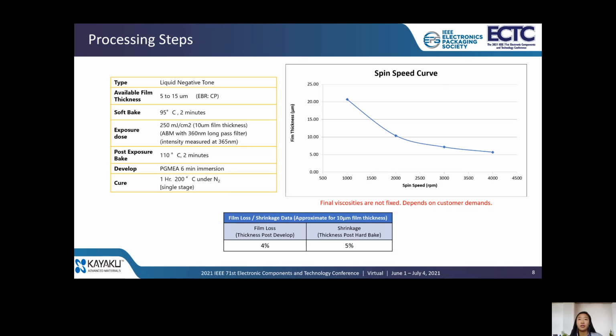After soft baking, this material undergoes a cure step via photoinitiator to cross-link the material. We recommend a 250 millijoule per centimeter squared exposure dose for a 10 micron film thickness, followed by a post-exposure bake at 110°C for 2 minutes, and this again is optimized for a 10 micron film thickness. This can obviously be optimized further for other film thicknesses. After PEB, the wafer undergoes a development step, which is recommended at 6 minutes for immersion for a 10 micron film thickness to achieve a 1:1 aspect ratio. The development step will clean out any unexposed areas of the wafer. Finally, the material requires a cure step of 200°C for an hour under nitrogen to ensure a full cure.